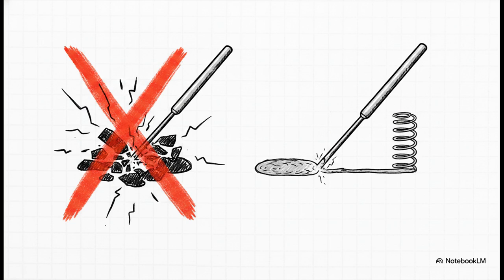If you were to try and use a mild steel electrode on cast iron, that weld pool would just soak up all the free graphite, harden into glass, and crack before you even had a chance to flip your hood up. Nickel stops that from happening.